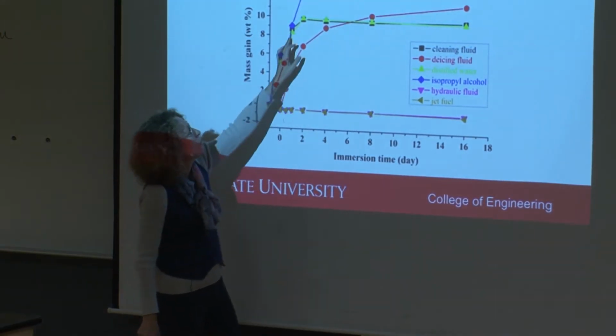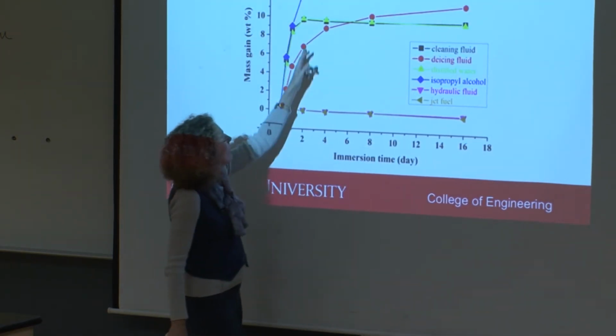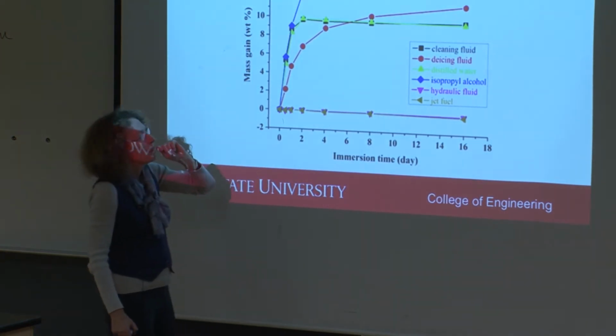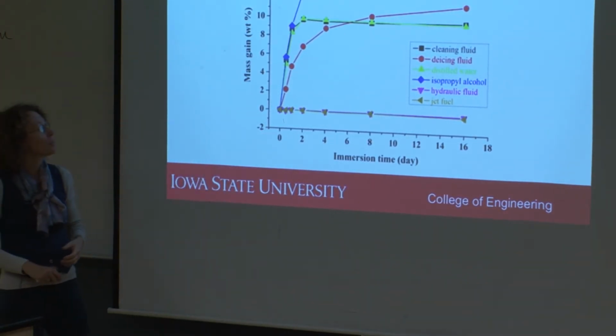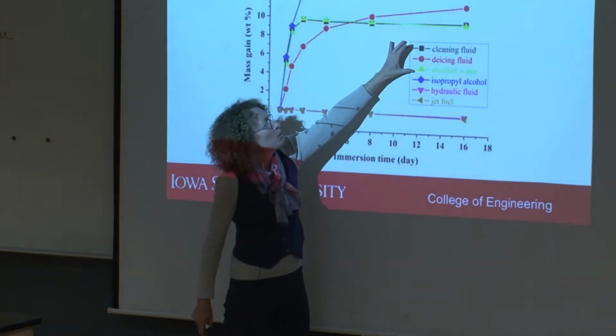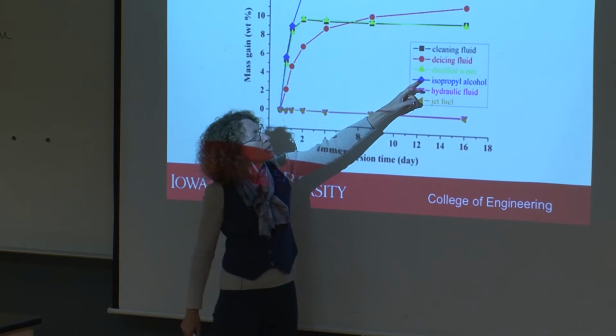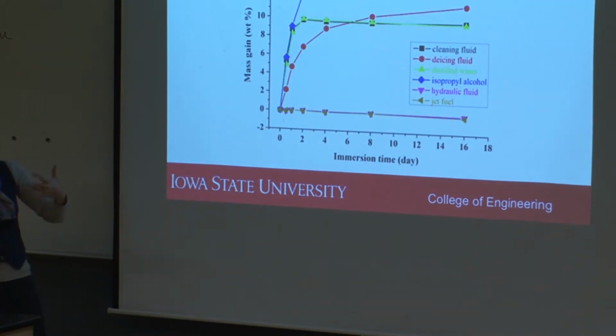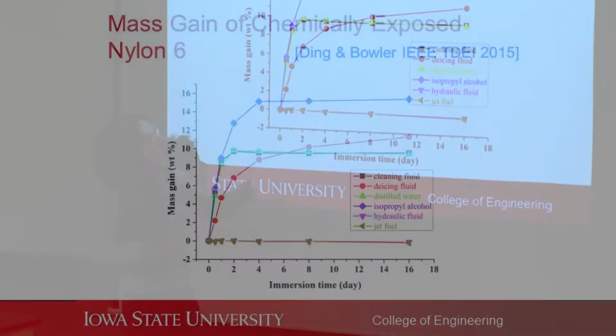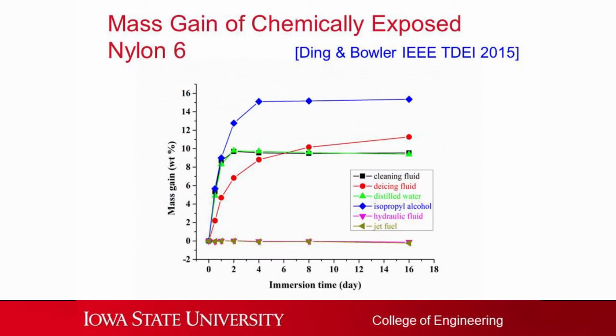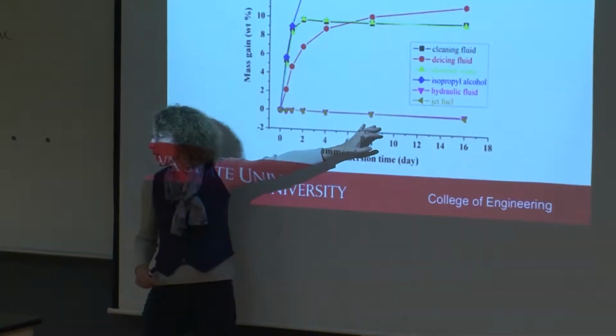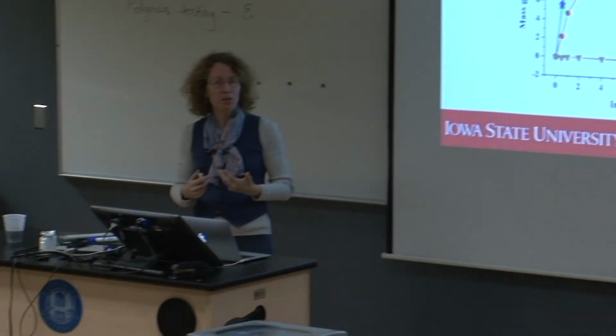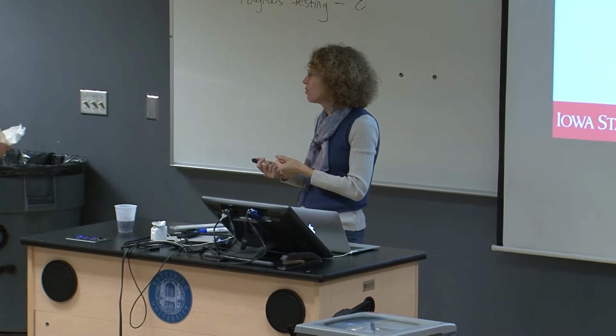Let's pick water first, which is the green one. So in distilled water, you see the mass increases up to a couple days, and then it's pretty much stable after that. But it's obviously taken in water molecules into the system. The black line, the cleaning fluid, follows a very similar pattern. The blue one, isopropyl alcohol, there's some interaction going on that means there's a greater mass gain for that one than the others. Deicer, still quite a gain, but it's slower, it takes longer. And then the other two, these are hydrocarbons. They are not water-based. Hardly anything happens at all, okay? So actually this measurement gave us a real clue as to what we might see in the electrical properties of the material as well.